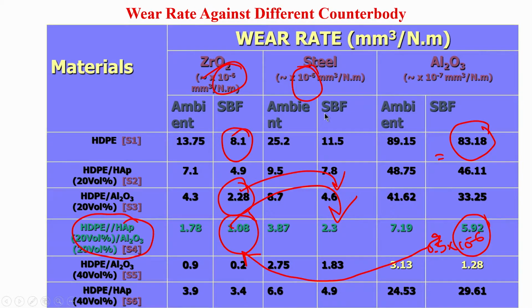Typically our observation is that in case of alumina the wear rate in simulated body fluid is either comparable or reduced for a given polymer-ceramic composite composition, but in case of steel, typically the wear rate even in the simulated body fluid is higher compared to that measured with zirconia or alumina mating materials.